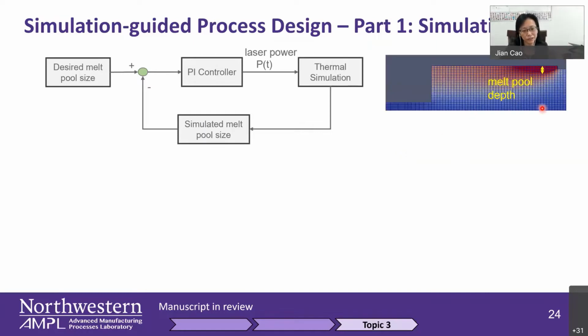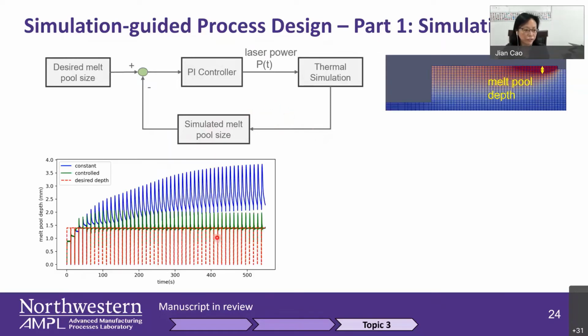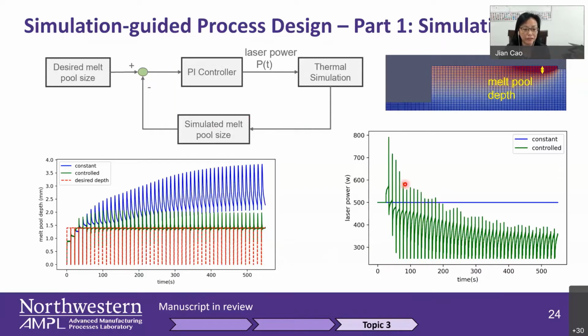So the idea is to use a simulation to calculate the melt pool depth, and then we can use a PI controller, for example, to actively change the laser power. Such that, for example, if it's a constant laser power, and we want to control the melt pool depth over the build with a certain height, you can change it, right, and make sure the melt pool depth is being kept. Otherwise, if you just use a constant one, you can see the melt pool keeps increasing.